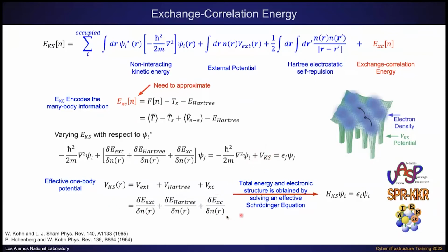And here you can see what's exactly input. So we have here the potential is built up of wherever the atoms are sitting, this Hartree potential, and then the remainder that we have to figure out. This then lends itself quite easily numerically, and there are many different codes that solve this problem. There's VASP, which is the standard for doing these first principles, quote unquote, calculations. There's a Green's function-based code, SPR-KKR, and also WIEN2k, which is an all-electron code for performing this task specifically. You're just solving this Schrödinger equation. That's all we're doing. It's just that the potential is very, very fancy in some sense.